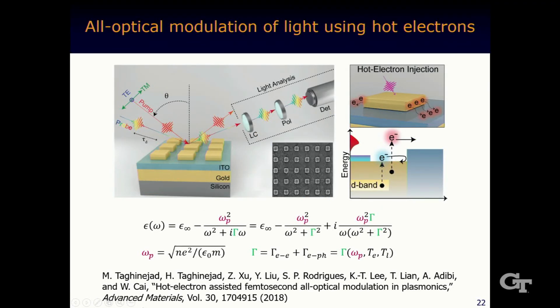So the first demonstration we are going to look at here is optical modulation of light using hot electrons. In this case, you have almost like a plasmonic absorber with metallic cubes separated from a gold layer by an ITO layer. First, this ITO layer serves both as a spacer and also a very good electron absorber so that the hot electrons generated in these cubes can escape from the metal and enter this ITO layer.